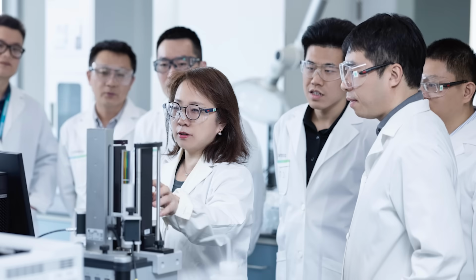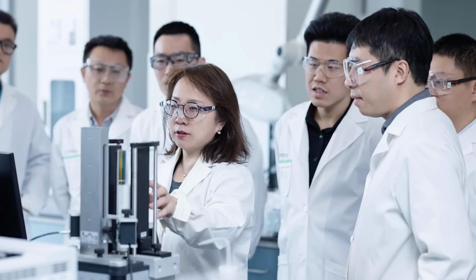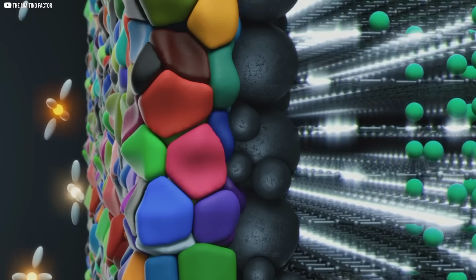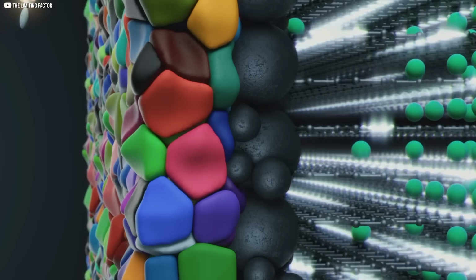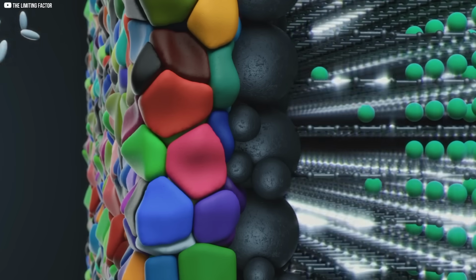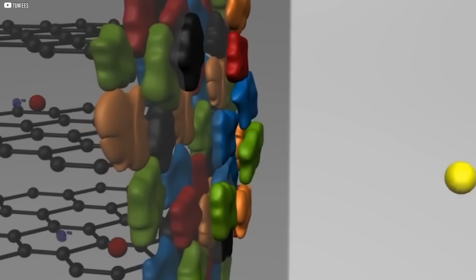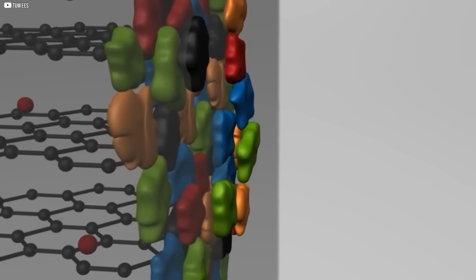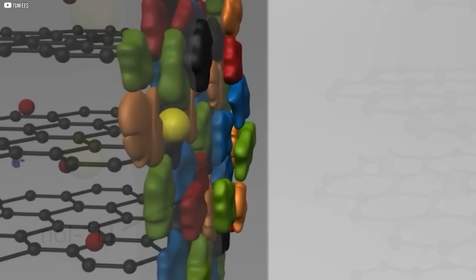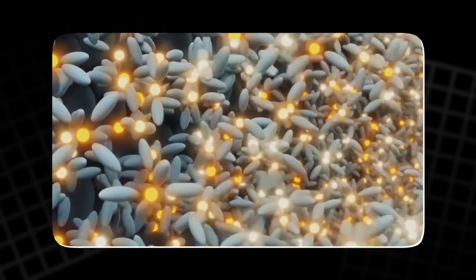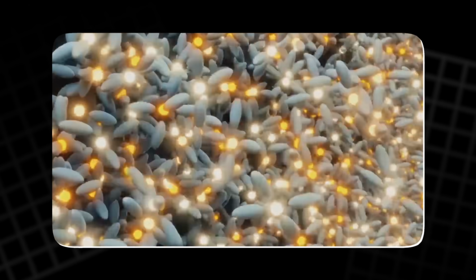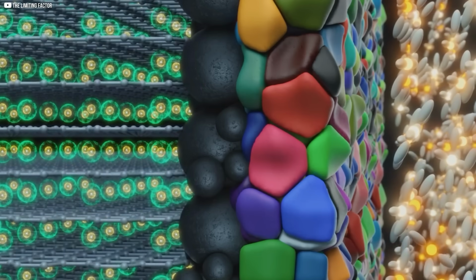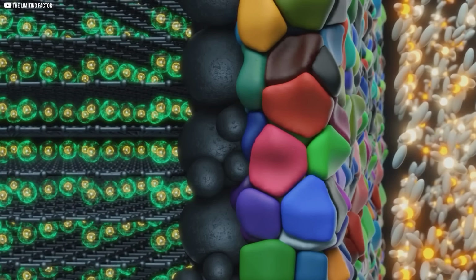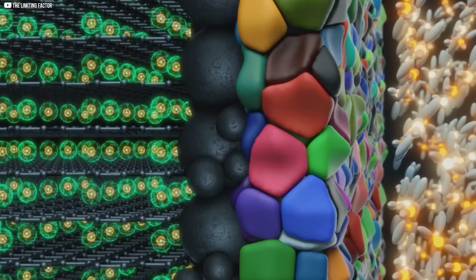The Beijing team's solution was deceptively simple. Coat the electrode surfaces with a microscopic layer of fluoroethylene carbonate. This created what battery scientists call a solid electrolyte interface, or SEI. Think of it as an invisible shield, thin enough not to impede ion flow, yet strong enough to guide aluminum into forming smooth, uniform layers.